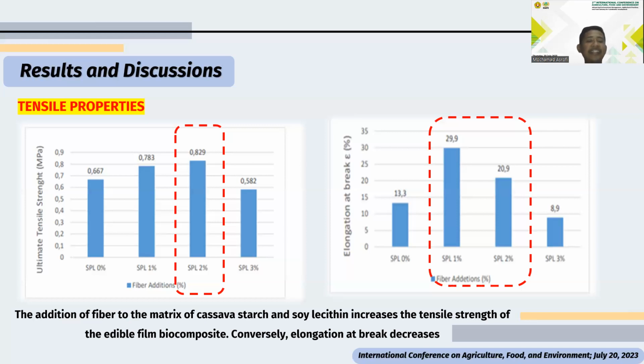But with the addition of 3% of fiber, the ultimate tensile strength decreases. This indicates maybe due to the agglomerated fiber in the matrix. So the best value of ultimate tensile strength was in the addition of 2% of sugarcane bagasse fiber in the cassava starch and lecithin matrix.